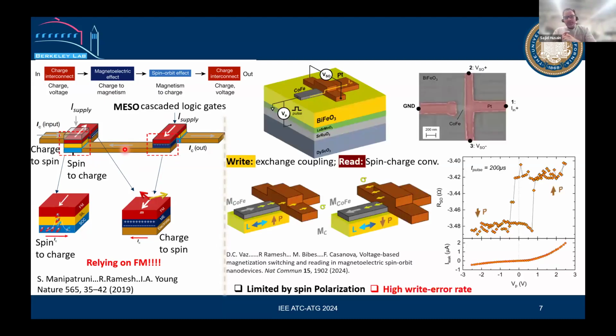That's the recent experiment done by Felix Casanova, Manuel Bibes and Ramesh, my group. That's the electrical control of the magnet I was talking about. The hysteresis on the right is the output voltage coming from the interaction between bismuth ferrite, a magnetoelectric material, and cobalt iron. The X voltage is the electric field going into the bismuth ferrite, and the output is the spin-charge conversion from cobalt iron to platinum. This peak-to-peak number tells you that you can switch the magnetization of cobalt iron using bismuth ferrite, and it is about 500 to 600 millivolt. I mentioned in my previous slide that we need 100 millivolt to reduce the energy to the order of 10 to the minus 18 joule.